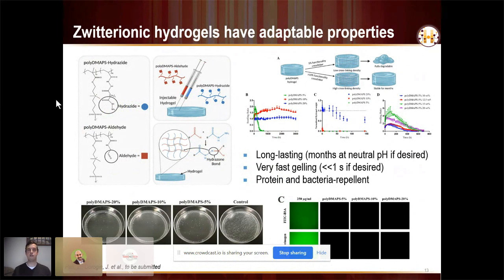So what we found in this material is that we can get hydrogels to form at very, very low functional group contents, 5 mole % functionalizations or less, and much lower polymer concentrations, which means the water content of the resulting hydrogels can be higher, but still get very fast gelation and very long-lasting hydrogels. So this is a really interesting almost interpenetrating network, or dual cross-linked, maybe is a more accurate term, structures that we can get.